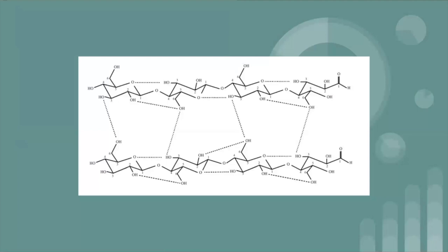Protofibrils of this glucose chain are extruded throughout the manufacturing process through the bacterial cell wall, where they combine to form nanofibrils or ribbons of cellulose. Now, these ribbons use a very porous matrix to create bacterial cellulose's web-shaped network structure. The cellulose that is produced has a large number of hydroxyl groups on its surface, as shown in the picture, which accounts for its hydrophilicity. It loves water, biodegradability, and ability to alter chemicals.